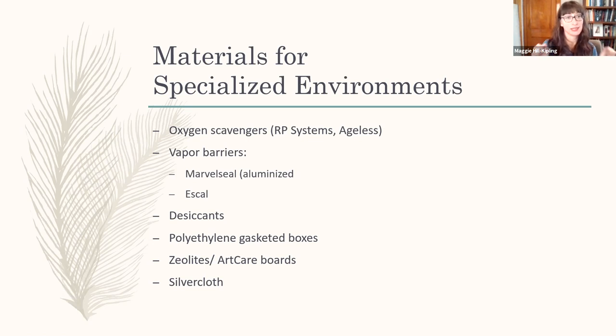But again, we do see some leakage of those, a little quicker leakage in terms of the humidity getting in. And those aren't as good for using with the oxygen scavengers because when the oxygen scavengers work, they reduce the volume significantly in a container. And so that would suck in, and then in those gasketed boxes, it ends up breaking that seal when it starts to suck in. And then you just get everything coming in, which may be part of the problem that we've observed with the gasketed boxes and the desiccants as well.